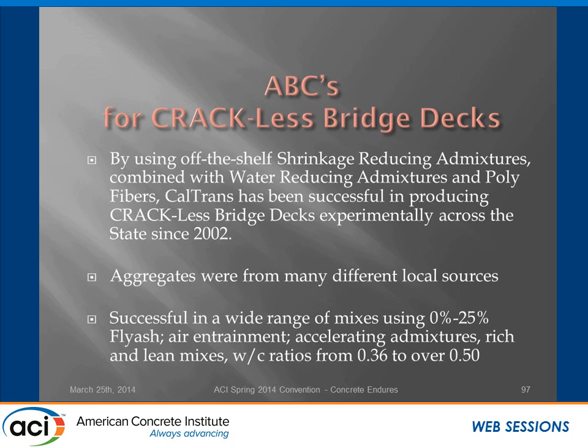So the formula again for a crackless bridge deck: these are off-the-shelf admixtures that are currently available. The polyfibers, we've been using macro fibers primarily on a lot of these efforts, but we are starting right now to use macro and micro fibers in combination. Aggregates are from various different local sources, as you'll see in a minute here, and we've used anywhere between 0 and 25% fly ash with air entrainment, no air entrainment, accelerated admixtures, water cement ratios from 0.36 to over 0.50, and had really good success.